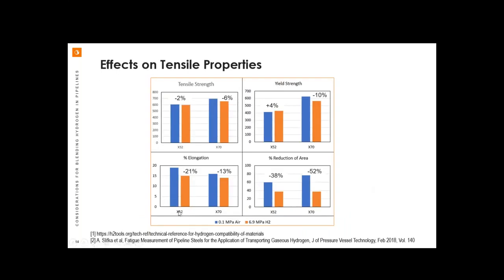So here's an example. I'm taking this from Hydrogen Tools website that quotes a lot of government data as example. We're looking at just a comparison here between an X52 pipeline steel and an X70 in all cases. The blue bar is the test done in air. And the orange bar would be the test done in about 7 MPa hydrogen or 1 KSI hydrogen partial pressure. Tensile strength values don't change much, nor do the yield. It's all within about 10%. The alarming values for relative difference are elongation and reduction of area, and some of them are pretty big. So yeah, that's not great.